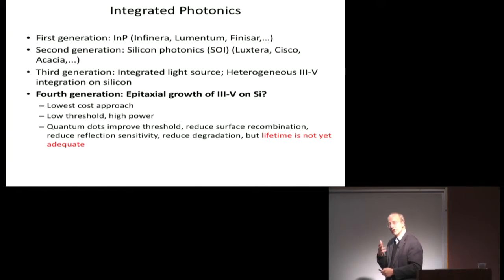So again, when you grow III-V on silicon, it's not lattice matched. There's large dislocation densities, and dark line defect growth during that is a big problem. So quantum dots gain you immediately about a factor of 10. You get 10 times better lifetime by using quantum dots rather than quantum wells. But it's not yet adequate. So these first three are all viable approaches. They're all competing in the marketplace. This last one is not ready for prime time yet.